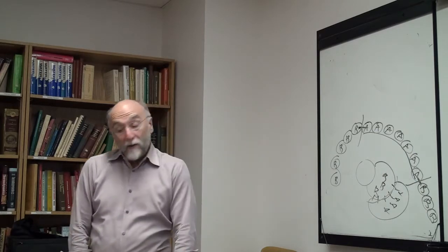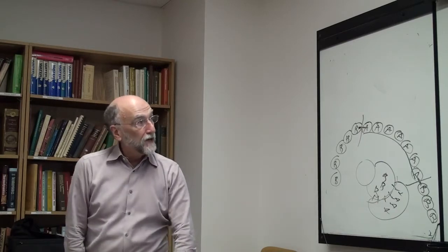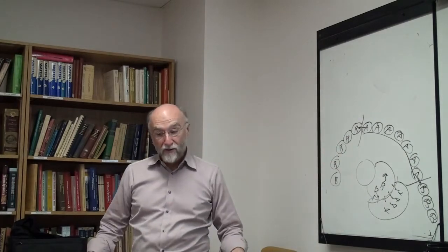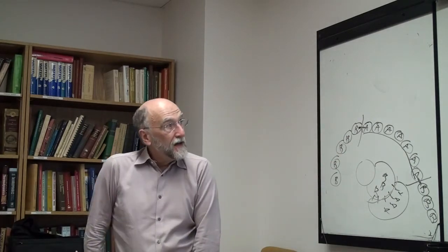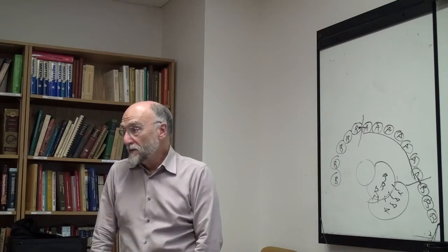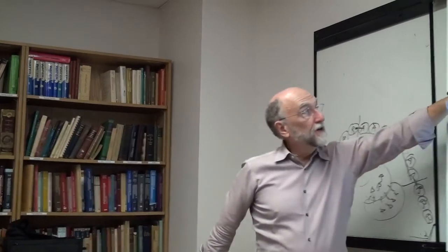We could discuss that, but anyway, the point is that with Z equals 2, mathematically you do not get the miscibility gap, but with Z equals 6, doing it correctly, or with molecular dynamics, or Z greater than 2, you do in fact get the miscibility gap, and you also get it with the approximate equation. So there are 2 ways of getting a miscibility gap. One is to have Z greater than 2.